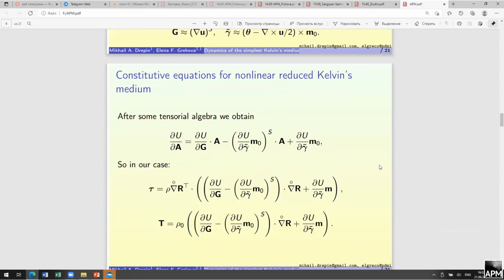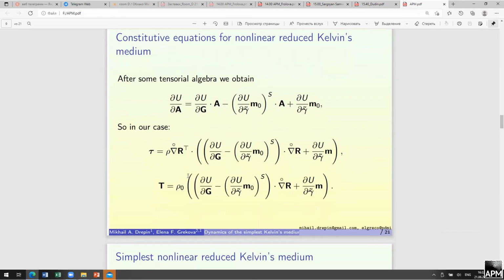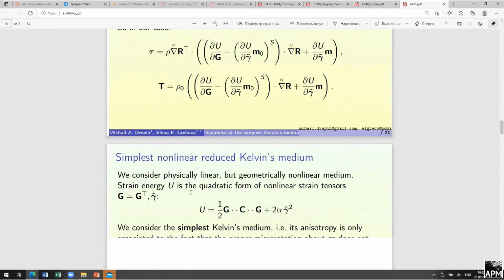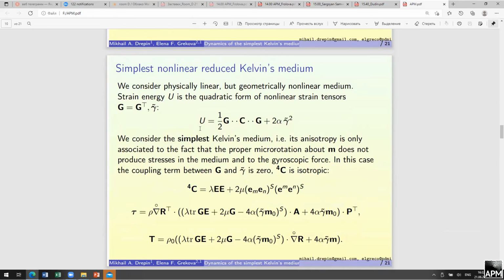So after some tensor algebra, we obtain our tau and T. So we consider a physically linear but geometrically nonlinear medium. Strain energy is a quadratic form on nonlinear strain tensors G and gamma. G is a symmetric tensor, and there is no term with G and gamma because of isotropy of our medium.